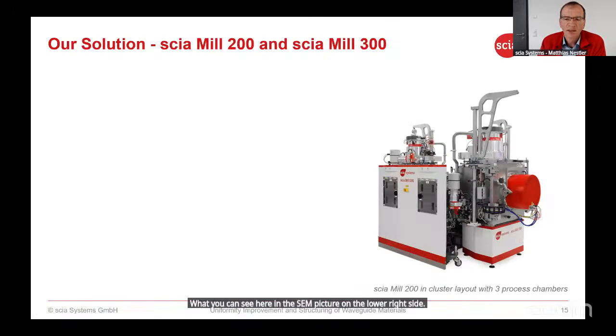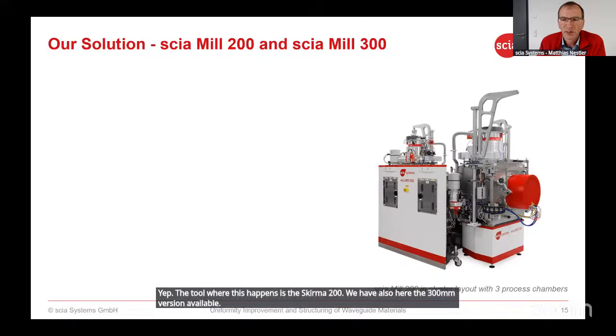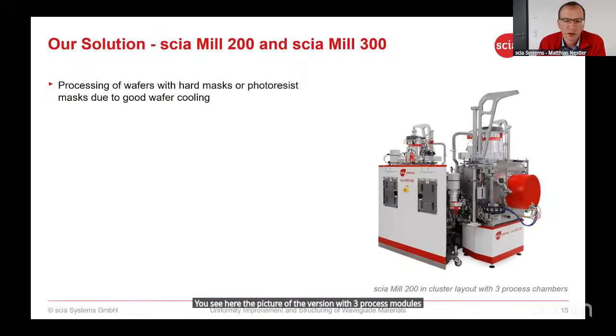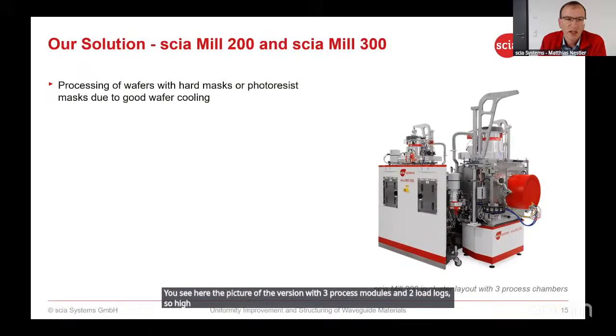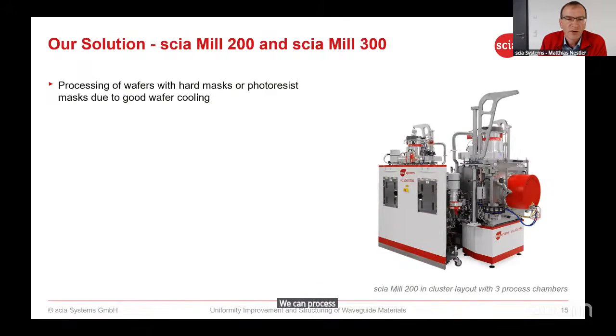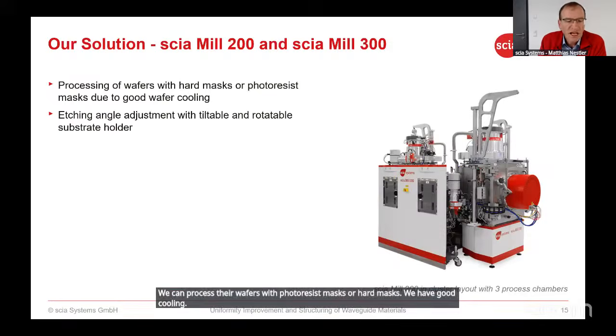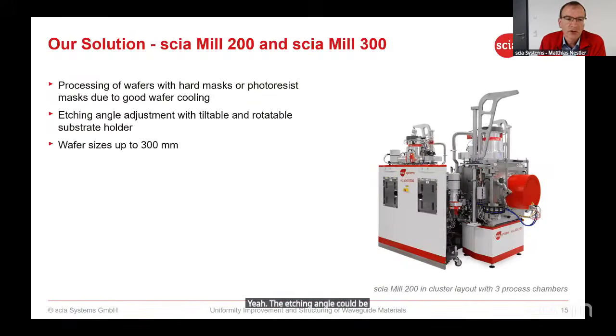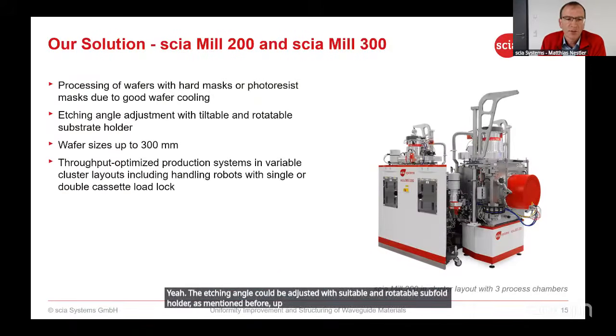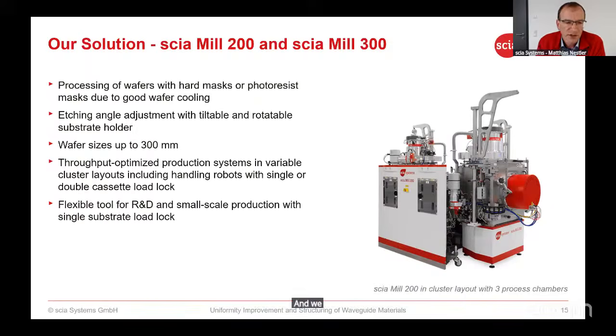Yeah, the tool where this happens is the Scia Mill 200. We have also the 300 millimeter version available. You see here the picture of the version with 3 process modules and 2 load locks, so high volume manufacturing ready. We can process wafers with photoresist masks or hard masks. We have good cooling. The etching angle can be adjusted with a tiltable and rotatable substrate holder, as mentioned before, up to 300 millimeter. I also mentioned we optimized the system for high throughput with that robot system and multiple modules. And we also have versions as a flexible tool for R&D and startup companies with just a single load lock available.